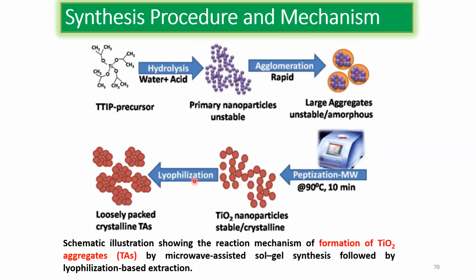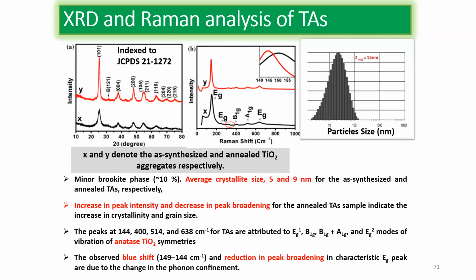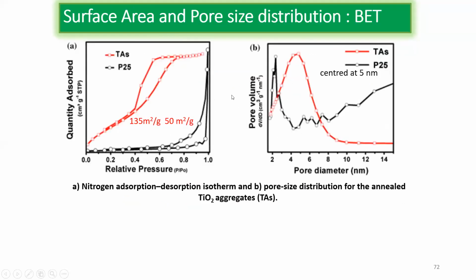Lyophilization is a sublimation process, in which the frozen liquid directly turns into vapor, and because of lyophilization, I can get some aggregation in the material. But as it is at a low temperature, I think around -191, it does not give packed aggregation, it gives loosely packed aggregation. So overall, we designed a good material which is loosely packed, and these are some XRD and Raman characterizations. To check whether it is loosely packed or not, we performed BET analysis, and we found that the surface area of the material is really much higher than normally available particles. It has almost increased by 2-fold.